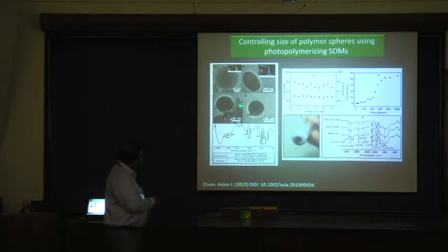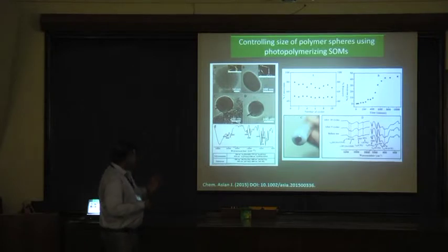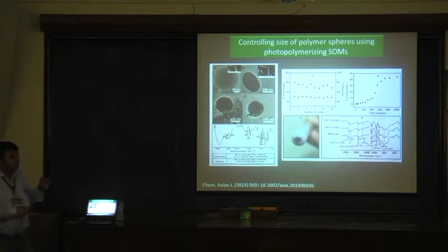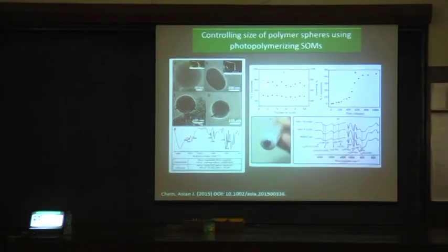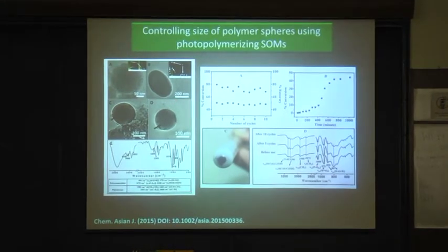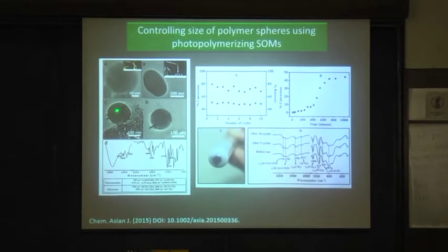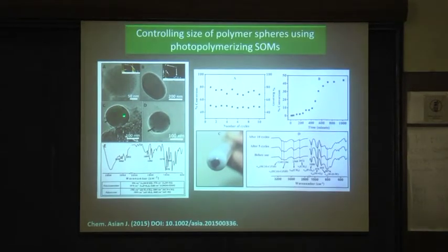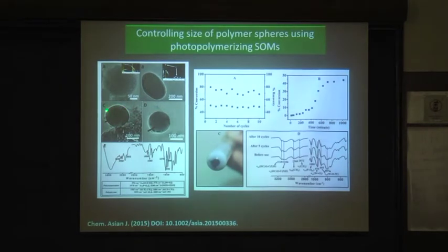This is, for instance, the cryo-TEM image of the SOM vesicle, and this is the EDX. Now, because it is a vesicle with water in it, as we probe it with the electron beam, it undergoes a deformation. But after some time, when it is polymerized, this is not very visible. It has an inner shell and a polymer shell, and as time goes on, the polymer shell gets thicker and thicker, and then it does not suffer that beam damage. So that means it starts getting stabilized.